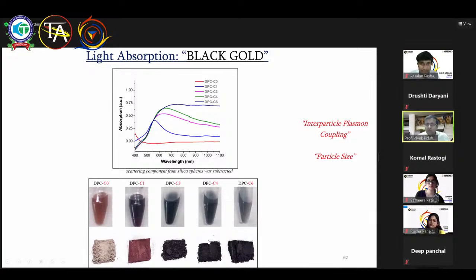So you can see the gold becomes black now because of this interparticle plasmonic coupling and the particle size effect. So black gold is gold, metallic gold, zero oxidation state, no doping, no functionalization. Still it is black because it now has the ability to harvest most of the sunlight. And that's why it's black.